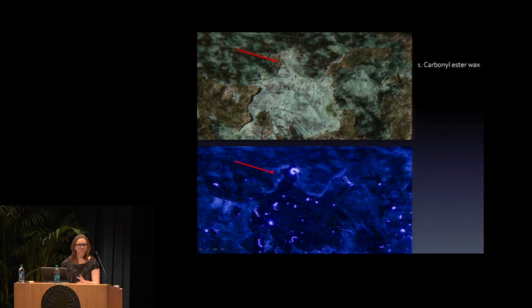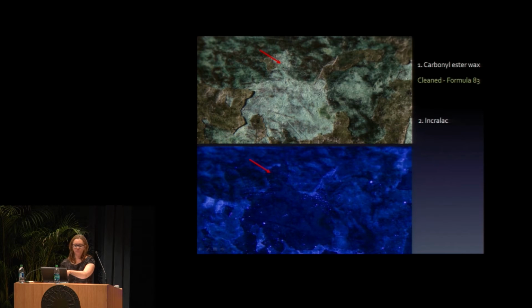So we took a different approach for sampling, and we would take a top layer, which you can see is a yellow crusty layer, took a sample, analyzed it with FTIR, and found an ester wax. But under UV, you could see that that wax was fluorescing white. So once I sampled that, you could see an area that didn't fluoresce. And so I cleaned the area that was fluorescing white and removed it based on UV using a Formula 83 as just a hydrocarbon blend. We analyzed that layer again, and it was Incralac.